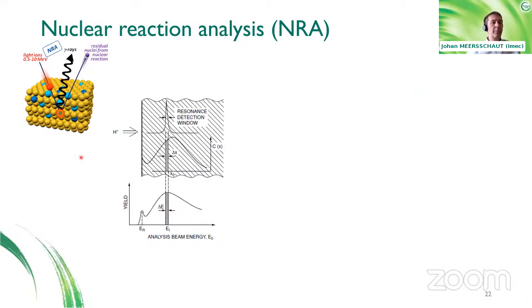And sometimes these processes are very narrow in energy. So if you then, with the electrostatic accelerator, tune the energy to an energy which is above the nuclear reaction energy, then the ion will first lose energy while penetrating into the material until it reaches the resonant energy.